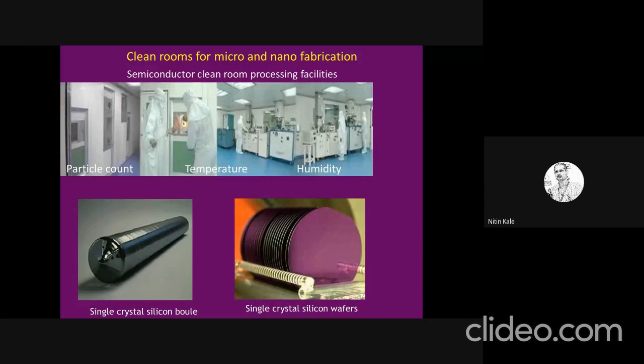And you do what is called a crystal growth process, wherein you have a base crystal that is inserted into the molten bath, and it is rotated. As you rotate it, it is slowly drawn out. Since when you draw it out the temperature is less, the melt is going to solidify. And when it solidifies, it's going to solidify as per the layout or the orientation of the crystal, because you have, again, thermodynamics issues. That's the minimum energy level at which it's going to have the minimum energy. So it solidifies slowly into a single crystal. And as you draw out, you can have a huge boule. The length of these boules could be 2 meters, so more than a person's height of 6, 6.5 feet.